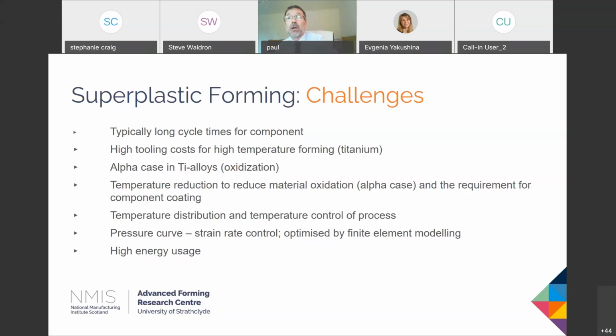And because superplasticity, the optimum superplastic properties are only obtained within a fairly tight range of temperatures, we need to have reasonably good temperature control of our apparatus, and we normally would aim for plus or minus 10 degrees C. And in the little video that Stephanie was showing you earlier on, the thing that we're actually taking out of the press there was, in fact, what's called a search blade. So that's a blade that had been put into the tools to actually measure the temperature across the whole tool setup to ensure that we were hitting our temperature control limits.